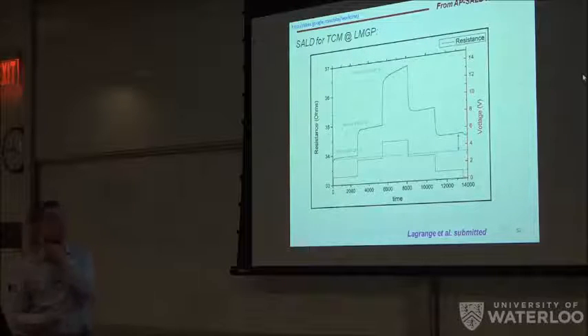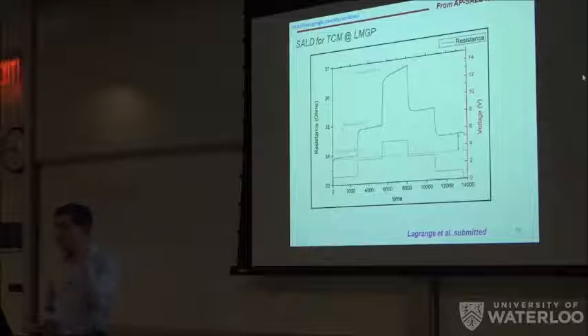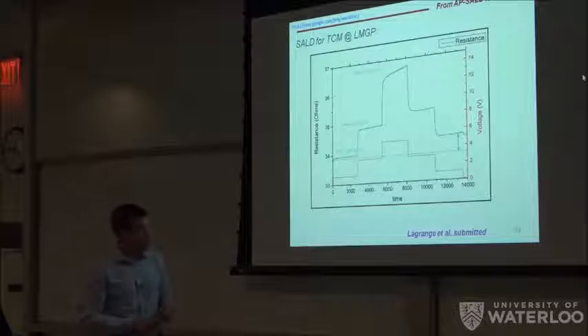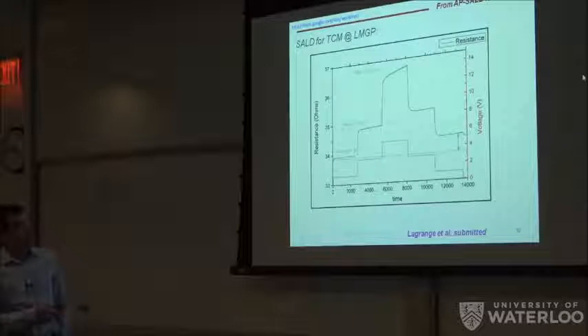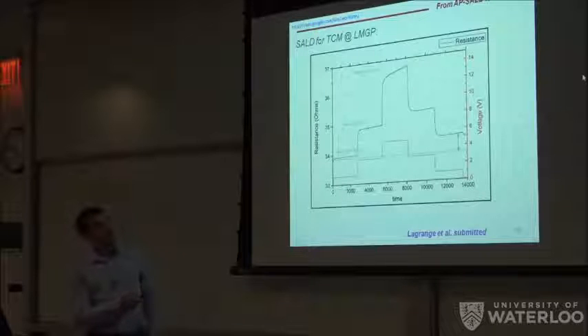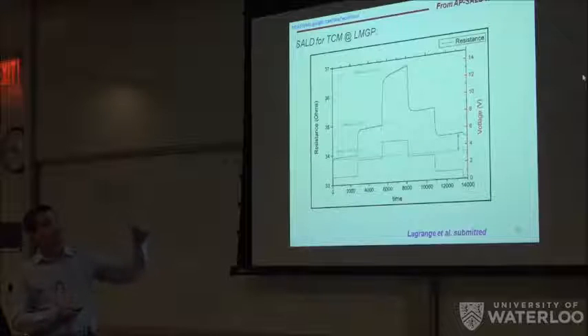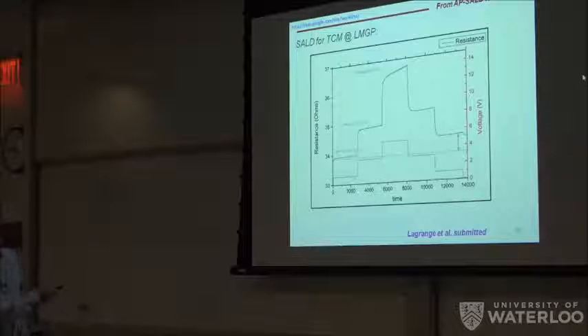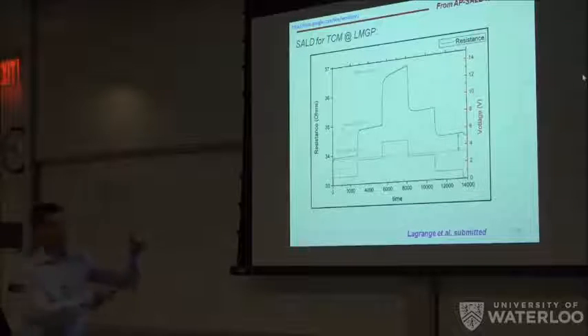So that's bad, because one of the applications of this type of TCNs is as transparent heaters to defrost the screens of motorbike helmets or for the planes, windshields. And you can see here, for instance, if you apply a voltage to your network to try to increase the temperature, the resistance you get as a result of the increase in temperature is not constant. It is evolving, and the higher the voltage, the faster is this increase in resistance, which means that your network is not stable. You should reach a resistance value for a particular voltage that should stay still, which would mean that you get a stable network, which is not the case.